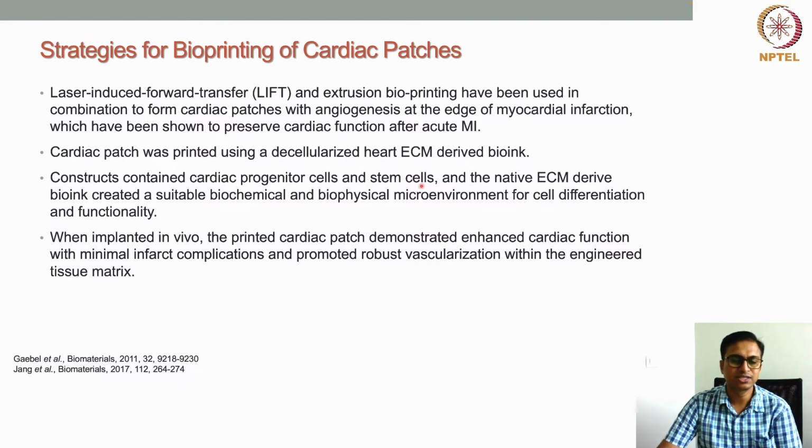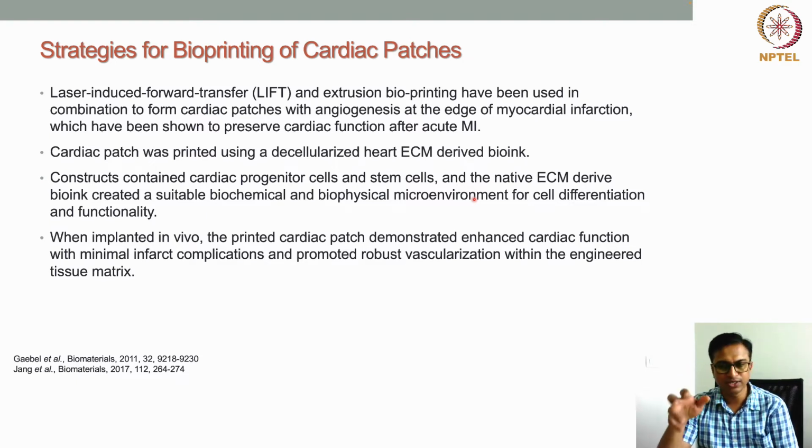So the stem cells can differentiate towards these cardiac lineages, because this decellularized ECM bioink also has resident growth factors and bioactive factors that induce differentiation of these cells. And another important thing is, when they implanted this cardiac patch, generated by extrusion based bioprinting with the decellularized tissue specific bioink, it showed enhanced cardiac function with minimal infarct complications and promoted robust vascularization within the engineered tissue matrix.